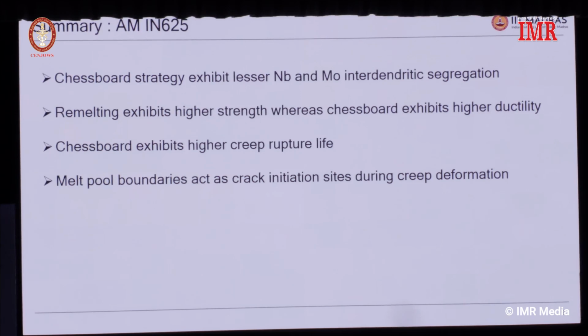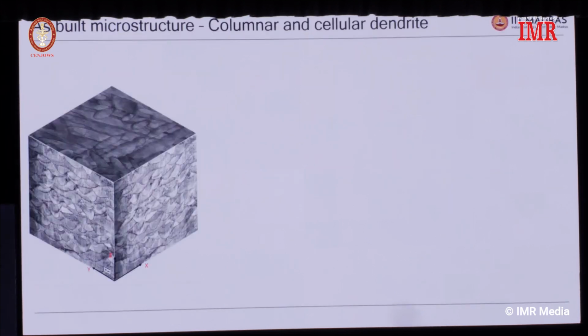So just to summarize the work on Inconel 625, the chessboard strategy gives less segregation, which is better. Probably it is giving a better creep rupture life because of less segregation. And what we have been working on, as part of an MTech project, is that the melt pool boundaries probably act as crack initiation sites for the creep deformation. Let me go to the Inconel 718.